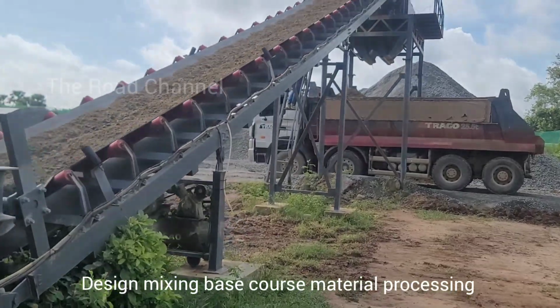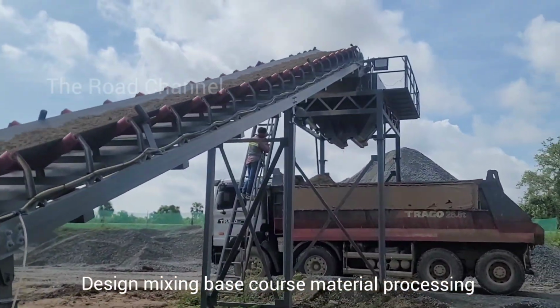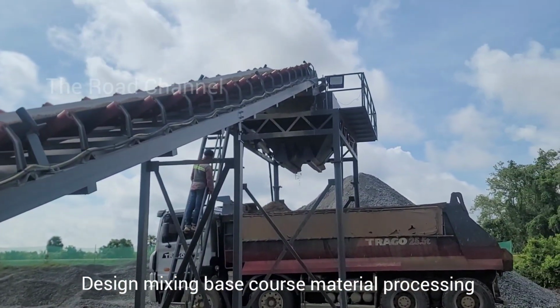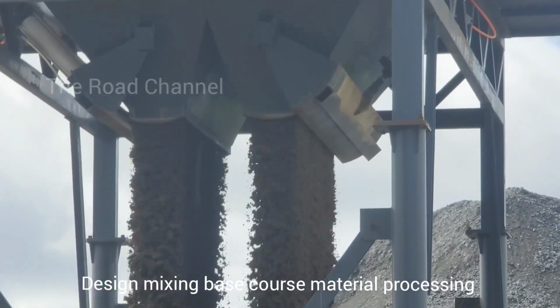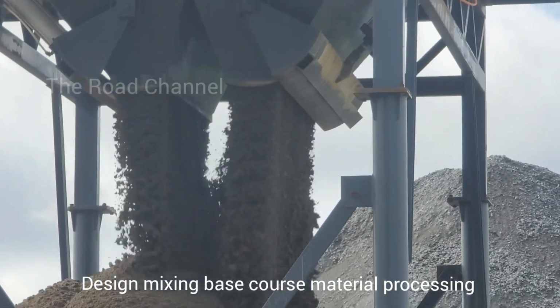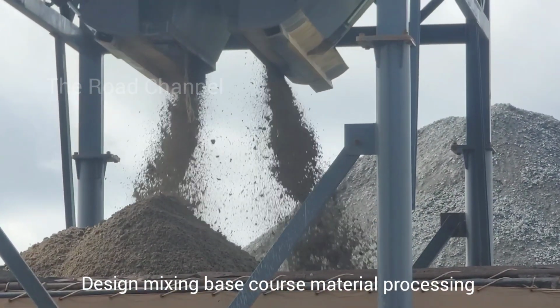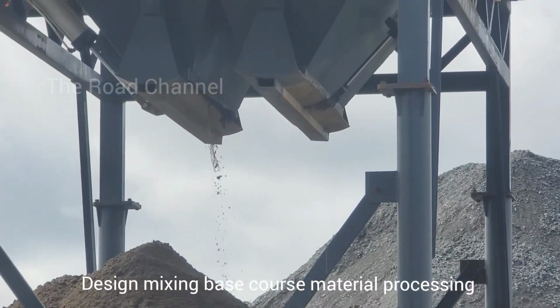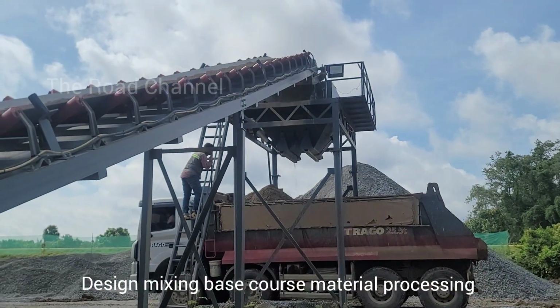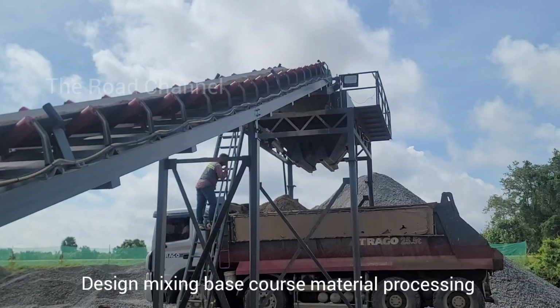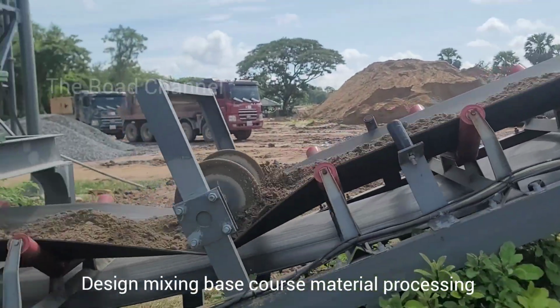Example gradation specification, AASHTO. Coarse aggregate, 20 mm to 5 mm, 60 to 70%. Fine aggregate, sand, less than 5 mm, 30 to 40%. The mix should generally follow a gradation curve that maximizes compaction and minimizes voids.